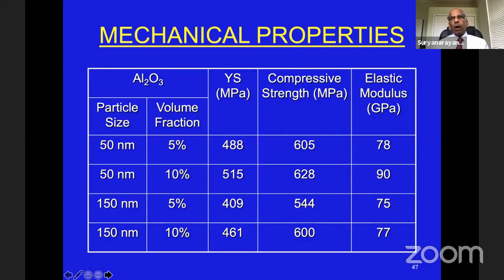And I'm not going to show all those details here. But if you now consolidate those materials and then measure the properties, yield strength, compressive strength, elastic modulus, depending upon the particle size, whether it's 50 nanometers or 150 nanometers, 5% and 10% in this particular case, you can see the modulus increases with increasing volume fraction of the reinforcement, and the actual yield strength also increases and the compressive strength also increases. So obviously there is a significant improvement in the properties.